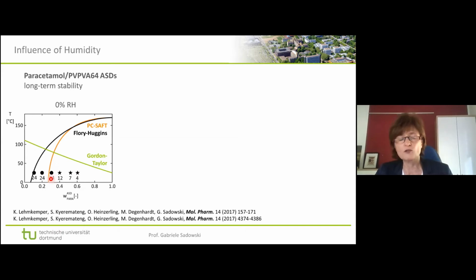Driving force is very low to crystallize, and you can indeed see it takes quite long. And of course, this is a sample we are very curiously looking at from time to time, and hopefully we will see crystals within the next year, so to say. So that means as long as we do not find crystals left of the solubility line, we are fine. Right, we can find crystals or amorphous samples, particularly those very close to the solubility line, and we believe that this will crystallize. So what happens if we now increase relative humidity?